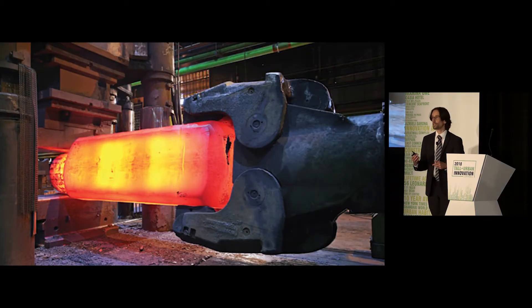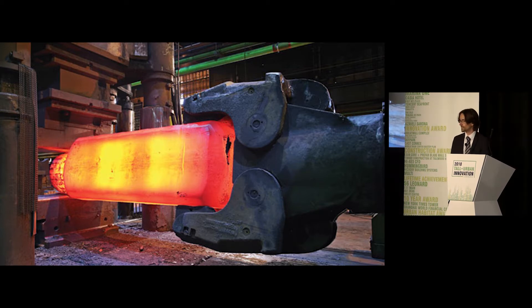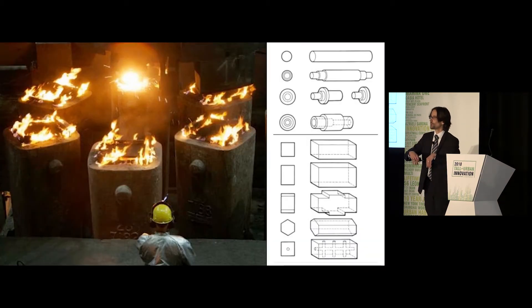So we looked towards a similar but different manufacturing process for Hudson Yards — we looked at the potential to use forgings. Forgings are similar to castings: we pour molten metal into a mold and it freezes, with the mold carefully shaped so that we get solidification from one end to the bottom. But the next step in the forging process is to heat the material up and actually crush it from every direction. That's a form of hot working, similar to plate, except we can do it in all three directions and get more uniform and isotropic mechanical properties.